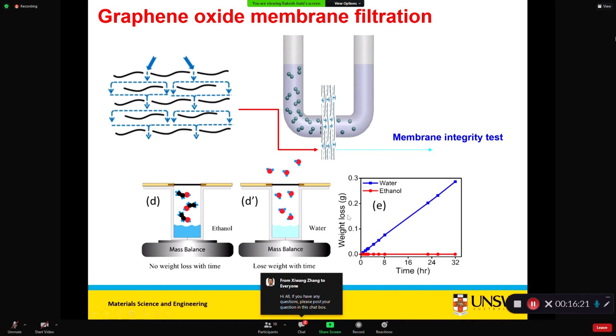Now what happens in the membranes, especially when the pore size is so small, is that the integrity of the membrane is very important. We want to understand whether whatever is being permeated is going through cracks or really through the designed pores. For that we have a very simple experiment, a mass balance. In one you have ethanol vapor, in the other you have pure water. From the weight change you can see that when you have water, you see weight loss, and with ethanol, no. It means the pores are only of the size of the water molecule. Even ethanol vapors cannot pass through pure graphene oxide membranes.